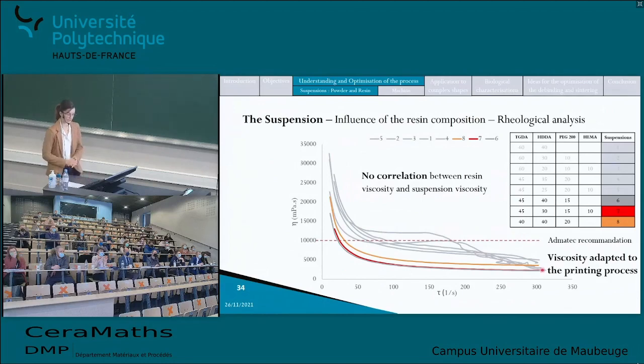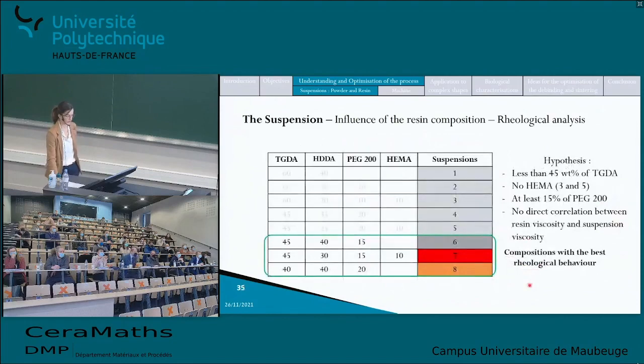So when I realized that, I started to make some assumptions on which monomers would work and which wouldn't work. So it appears that only the composition prepared with 45% of TGDA or less had a suitable rheological behavior. The use of HEMA, which can actually decrease the viscosity of the resin, didn't seem to have a direct impact on the viscosity of the suspension. At least 15% of polyethylene glycol 200 seemed to be needed. And finally, as I mentioned, there was no direct correlation between the resin viscosity and the suspension viscosity.